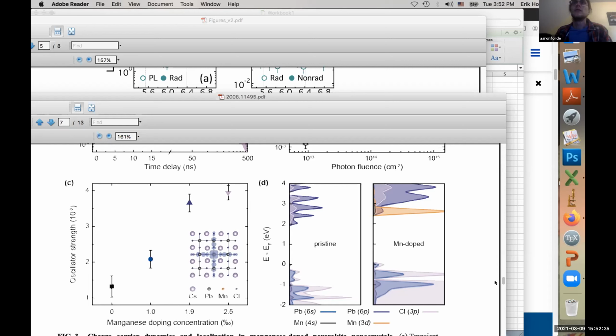Okay. Do you have any handle on the size of the exciton, or where the exciton is in your clusters with respect to the dopant? I understand it should be delocalized. So the excitonic wave function has two components: the envelope, from the boundaries, and the atomic centered sites. So I guess what they're saying in that paper is that the atomic centered sites are more dominant, with more localization to those, but the envelope function shouldn't really change because the boundaries don't change.